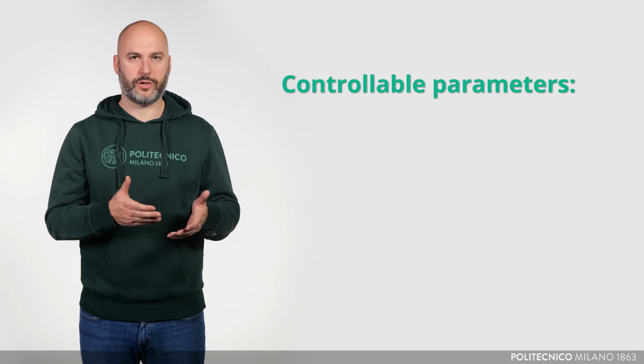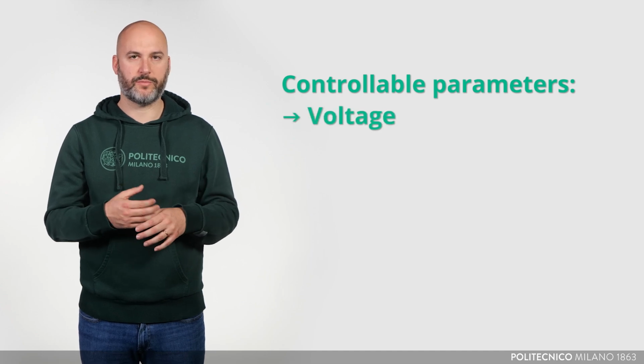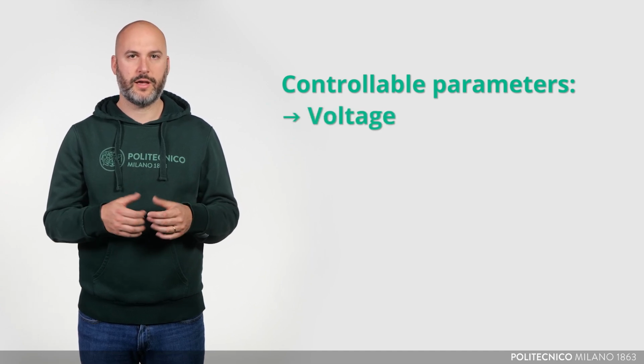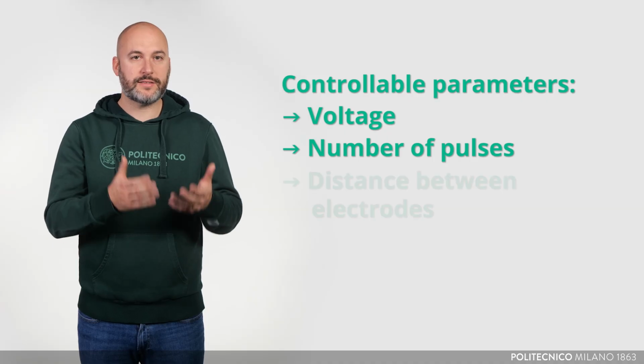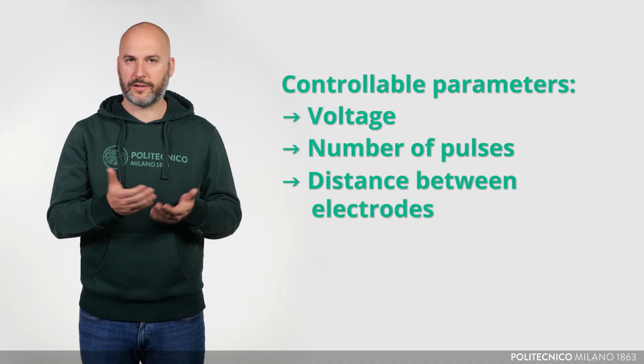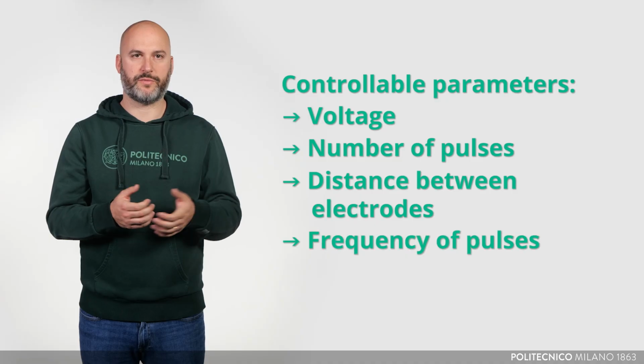High-voltage fragmentation is a wet process as the material is treated in water or deionized water, utilizing the higher dielectric strengths of liquids compared to solids during fast ramp-up times. At times less than 500 nanoseconds, solids break down more easily than liquids, allowing the liquid to act as a dielectric medium. This phenomenon is known as electrodynamic breakdown. Several parameters can be controlled, in particular the voltage, ranging from 90 to 200 kilovolts, the number of pulses, the distance between the electrodes, from 10 mm to 40 mm, and the frequency of pulses, up to 5 Hz. The whole process relies on the principle of electrodynamic fragmentation.